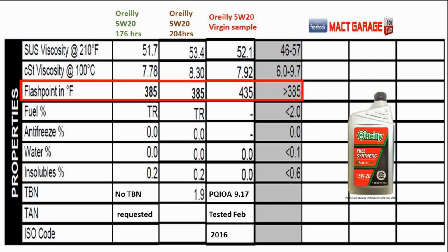Now here's the point where the virgin O'Reilly came in at 435 with the virgin sample, and both the Edges were at 385, and that is because, if we go down, we had a trace of fuel in the oil, and that fuel is going to cause you to have a lower flash point, which affected it. Now it's winter time, we're idling the engines more, and fuel gets in there because of idle, and you're going to have traces of fuel that cause it to go down.